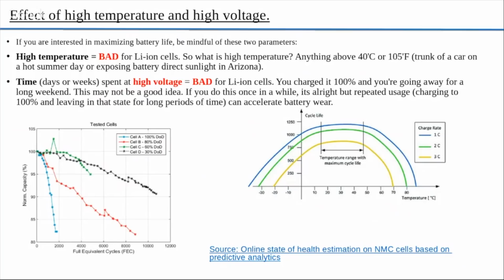There's a wonderful talk on YouTube by Professor Jeff Dahn. He goes into a lot more detail on why lithium-ion batteries die. But the gist, the takeaway from the whole talk, is that there are two things: high temperature is bad for lithium-ion cells, and the time spent at high voltage is bad for lithium-ion cells. If you have a practice of charging your Tesla or any electric car to 100%, you may want to rethink it a little bit, because charging to 90% will enhance battery life significantly. If you get 2 years extra, 3 years extra out of the existing battery just by charging to 90%, why not? And maybe in some cases, like long road trips, you can charge to 100%. That's okay.